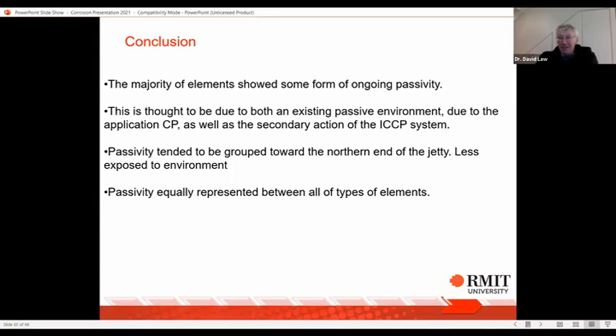So I said, out of that, we were able to see the majority of the elements had some form of ongoing passivity, which is presumably coming from those secondary effects from that cathodic protection. So it's both the passive environment due to the CP and those secondary effects. It was in the less exposed environment, but it didn't really run specifically across the types of elements, other than that one type, the back wall element, which for some reason was not being protected. That is perhaps because the tide is always hitting that back wall continually, and it may be a very aggressive environment, always having the tide splashing against that back wall, and perhaps that is why we weren't seeing any residual protection there, which again would suggest it's very much about those aggressive environments.